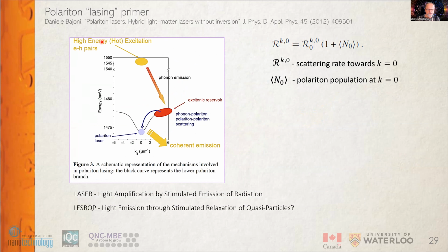You generate those hot excitons initially at higher K, and then they relax. So the polaritons, once in the lower polariton branch, actually have bosonic character, and this is very important because you can condense them at the bottom of the lower energy. They can condense as quasi bosons, and the rate of this condensation, as it turns out, is proportional to how many we already have there, and then they decay and emit this coherent emission.